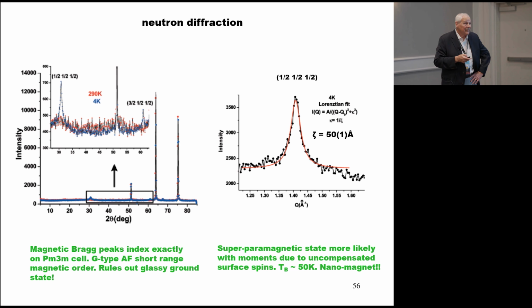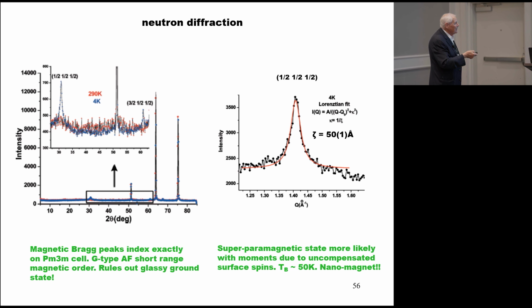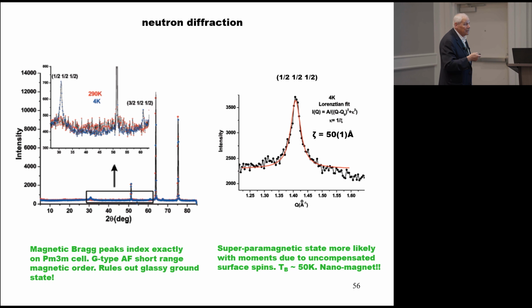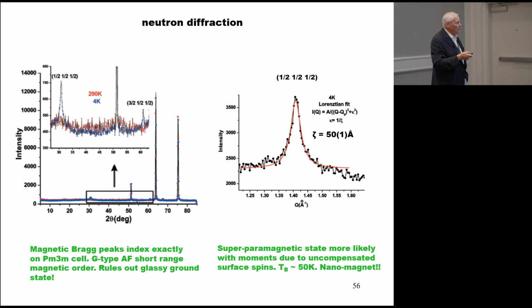When we look at the neutron diffraction, we actually see 2 magnetic peaks. The red data are at 290 Kelvin, the blue at 4 Kelvin. So we see 2 broad peaks that index just perfectly on the cubic cell. However, as you can see right away, they're much broader than the nuclear peaks, so they're not resolution limited. So we're looking at some kind of antiferromagnetic domain with a dimension of about 50 angstroms. We're calling this something like a superparamagnet. A superparamagnet is a cluster of a large number of spins. Normally these are ferromagnetically coupled, but if they're antiferromagnetically coupled, you could still get surface spins. There would be some fraction of the surface spins which will not be coupled to the bulk particle, so you can get superparamagnetic-type behavior.